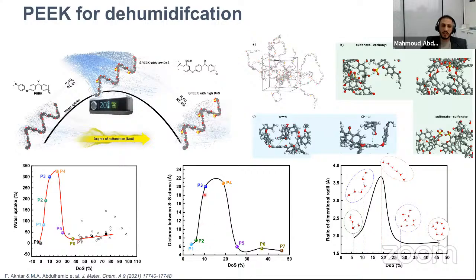The curve generated here results from the distance between S atoms. When you increase the degree of sulfonation, the SO3H groups are far away from each other. But at some point, they start to get closer, and closer, and very close when you have very poor performance. So this also fits into the structure-property relationship, to better understand how the material is behaving.